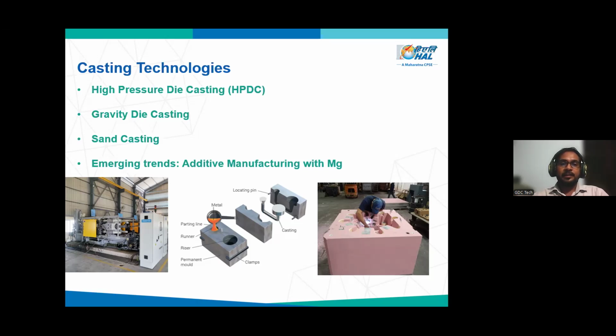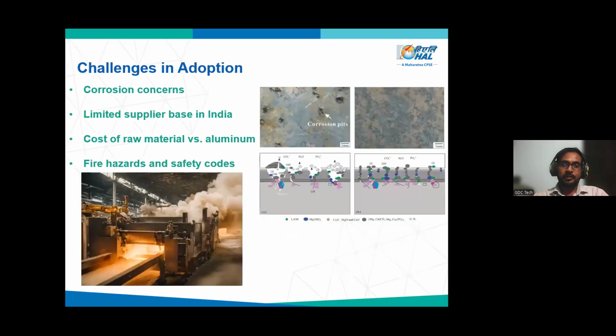Now, despite these advantages, magnesium does present some challenges. So let's talk about some of the points. First is corrosion. Corrosion is a key concern, especially in high humidity conditions and outdoor applications. Second, as I mentioned, India has a limited number of suppliers qualified to manufacture magnesium alloy castings. Third, magnesium is more expensive than aluminum. Even though the pure magnesium and aluminum rates are not very different, when we make alloys with rare earth and zirconium based hardeners, the cost of magnesium is far more than the aluminum alloys.